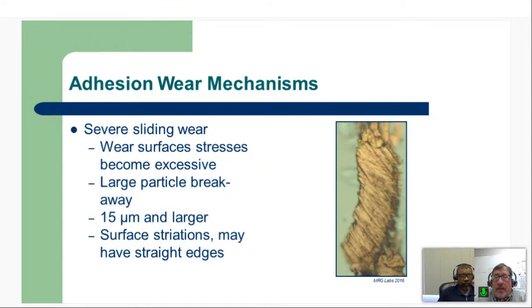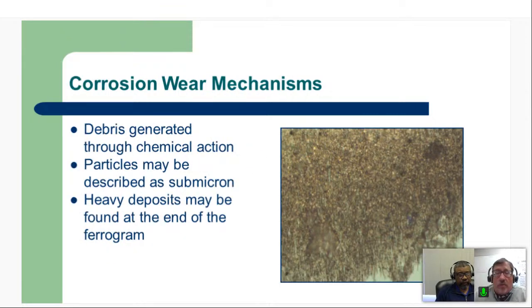Now, here's a nasty one where you've got these various lines, almost like the particles coming out, but the direction of contact is not in the same direction. It's a little counter to that. These are generally thought of as particles bigger than 15 microns. That's our cutoff between normal, although there are some small particles that we wouldn't want to call normal, but that's generally the trade-off to where we get into the severe wear mode of these larger size particles. And we'll show some of these, Richard will, when we put the microscope up.